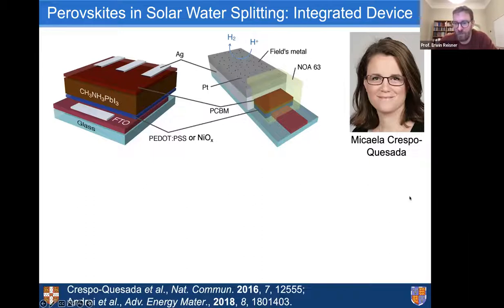So this is really our starting point. But in fact, Michaela started the encapsulation of the perovskite and pioneered this aspect in the group. And how did it actually start? It started because it became quite obvious to us that at some point we cannot ignore all the great light harvesting materials from the photovoltaics field. And also, just looking at solid liquid junctions, classical semiconductor photoelectrochemistry probably was not the way forward in terms of building functional devices. So at that time, there was quite some activity on protection layers. For example, we also worked with cuprous oxide. I've shown a slide at the very end, and there were some very nice papers at that time that you could just use atomic layer deposition to protect them. But we always found this rather complicated and thought there must be a much easier way to do this. In the beginning, we actually started with the cuprous oxide, but then we were just sitting there and thought, what's actually the most moisture sensitive light absorber for us to establish these encapsulation strategies? And we came quickly to the perovskites, and this is how we ended up there.